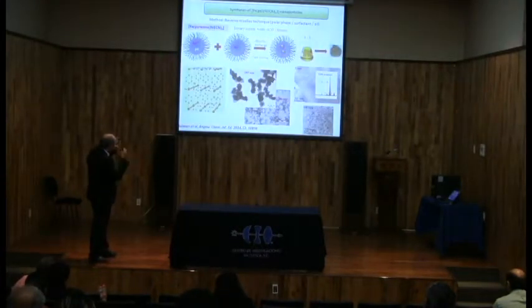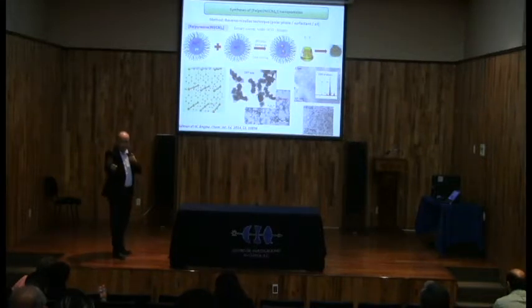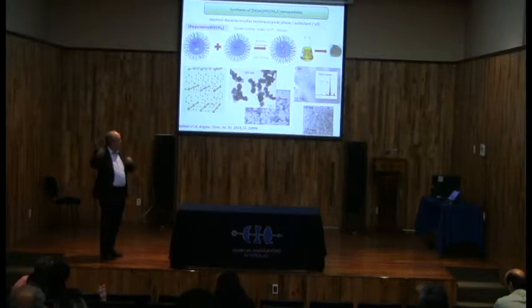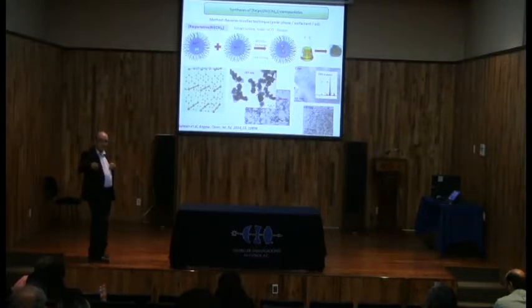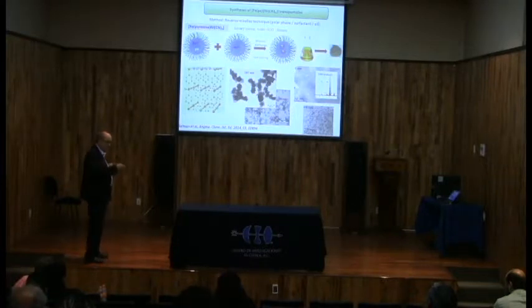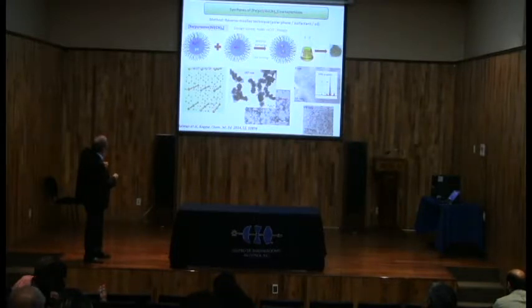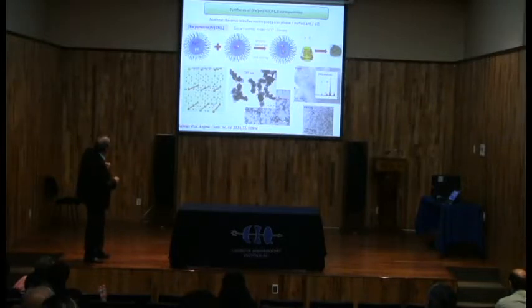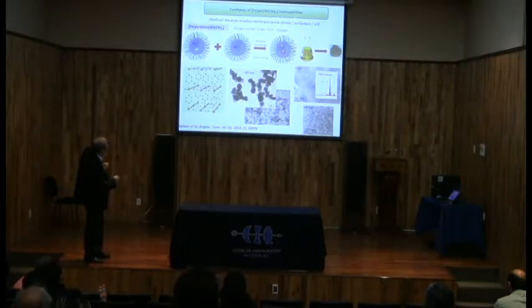So then the chemistry of this part is coordinated by Yonat Salman, he is present. So then we synthesized in the group nanoparticles of spin crossover. The approach is to use the reverse micelle technique by using surfactants and then by playing with the concentration. And then you have two reactors, two nano or micro reactors here. You have here the iron salt and the ligand, and you have here the nickel salt. And then if you combine this, you have your reaction here. And then by playing with the concentration, etc., you can have nanoparticles.